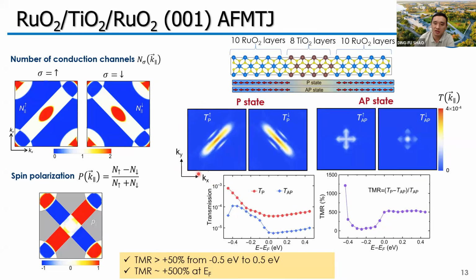And if we integrate the transmission over the momentum in the 2D Brillouin zone, we can get the total transmission. We find that the total transmission is always larger for the parallel state compared to that for the anti-parallel state, which leads to a positive TMR in the calculated energy window. The minimum TMR here is over 50%, and at the Fermi level, we got a TMR over 500%. This value is already comparable to the commercial ferromagnetic tunnel junction and clearly proves the advantage of using TMR to detect the Néel vector for antiferromagnetic spintronics, even though in this case we have only spin neutral currents.